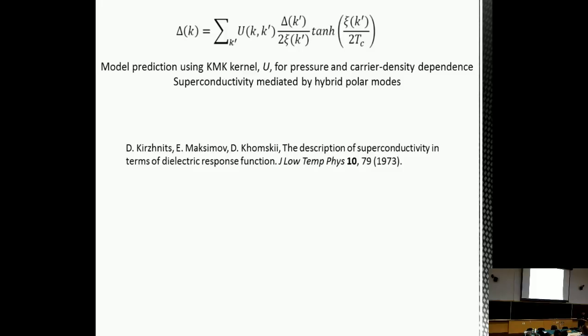So to see what happens for Tc, here we have just a weak coupling gap function, which can be solved self-consistently. On both sides, Tc is the superconducting transition temperature. And then for U, which is the interaction kernel, we use the kernel referred to in this paper, which is an approximation of the full Eliashberg equations for superconductivity.